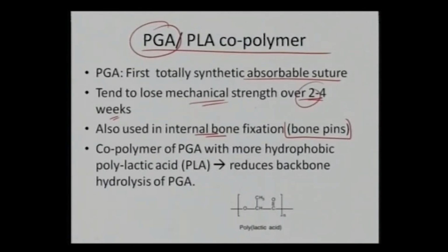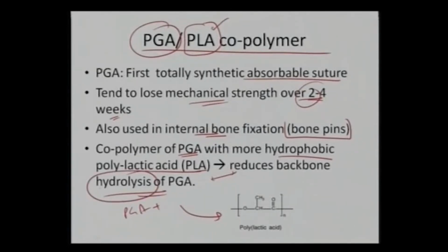So to conquer that, since PGA will dissolve in 2 to 4 weeks, we add PLA to it, because PLA is much more hydrophobic in nature. The copolymer of PGA combines with the hydrophobic polylactic acid, and that reduces the overall hydrolysis of PGA. So we have PGA in combination with polylactic acid, which is much more hydrophobic, and that reduces the damage caused by the hydrolysis of PGA. So the overall dissolution time can be extended beyond 2 to 4 weeks.